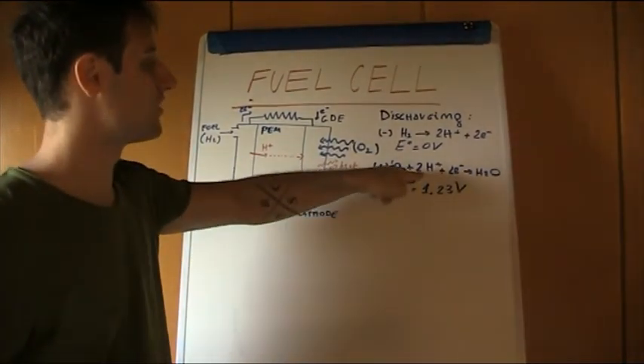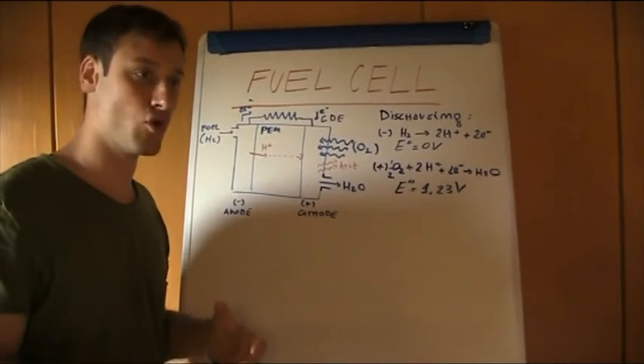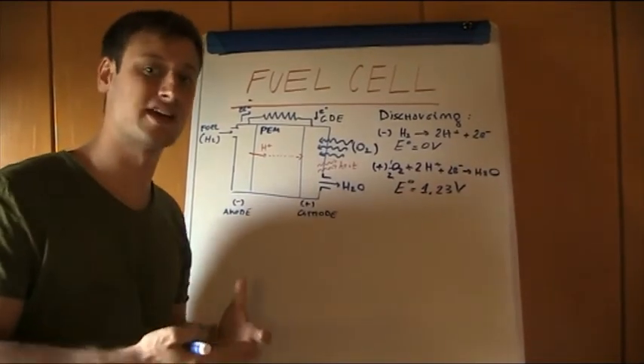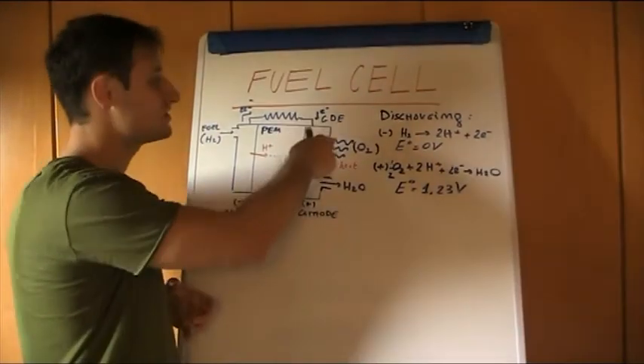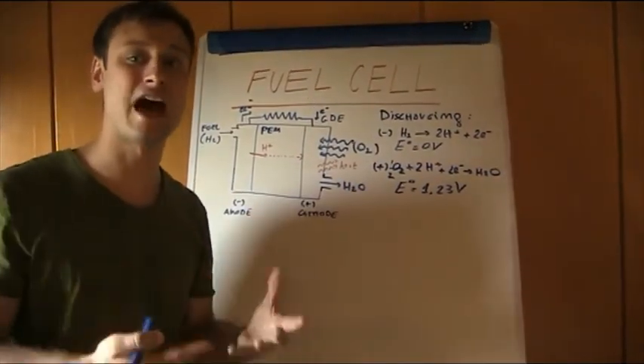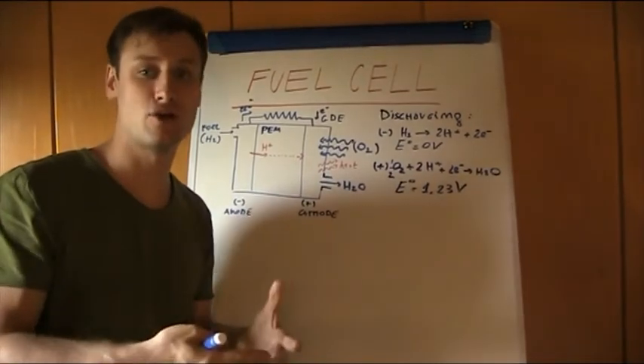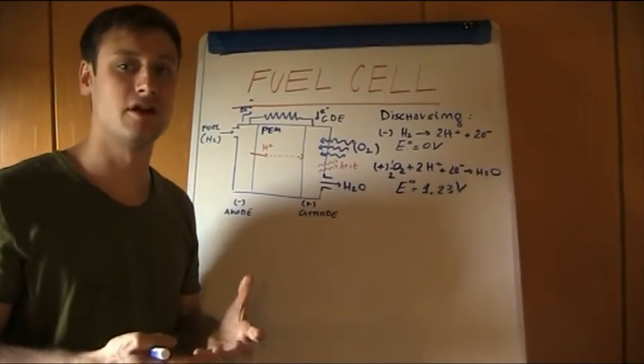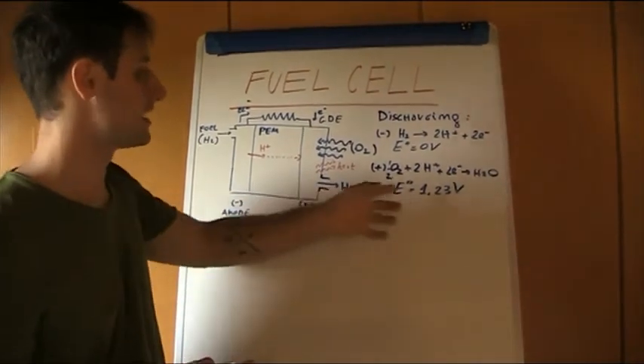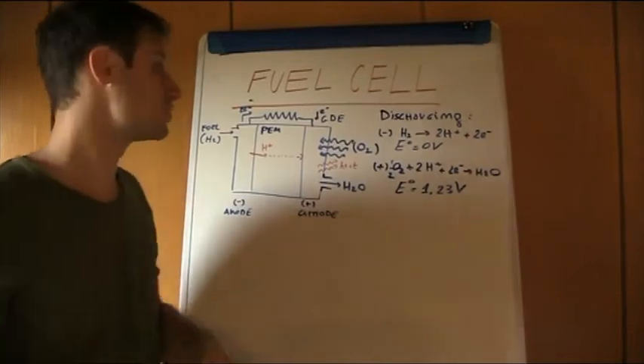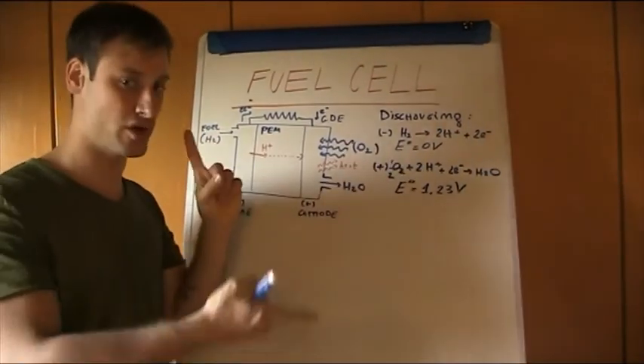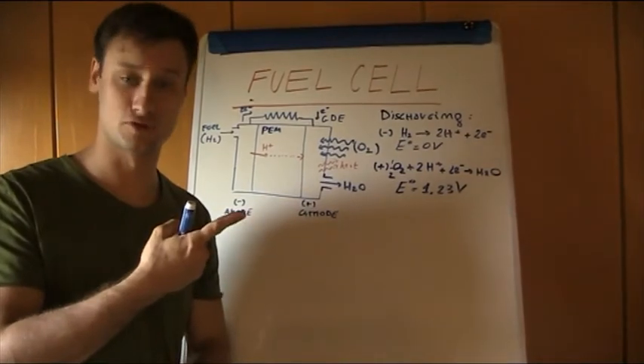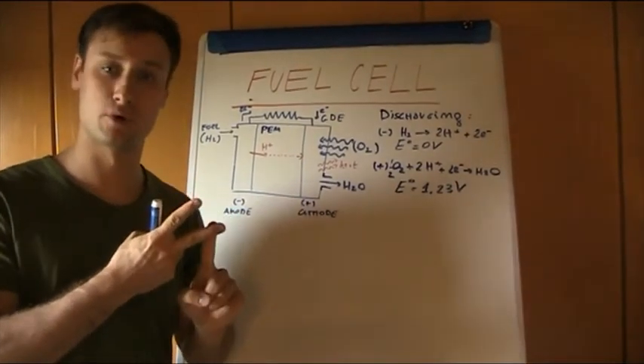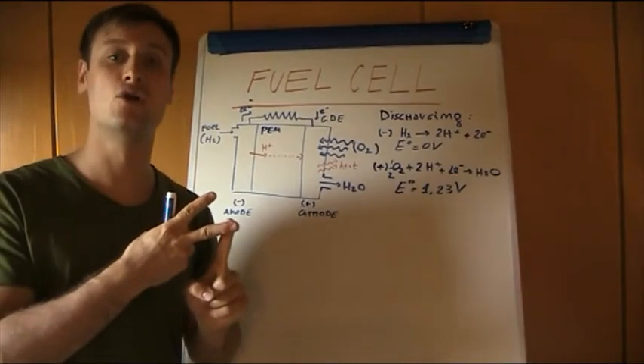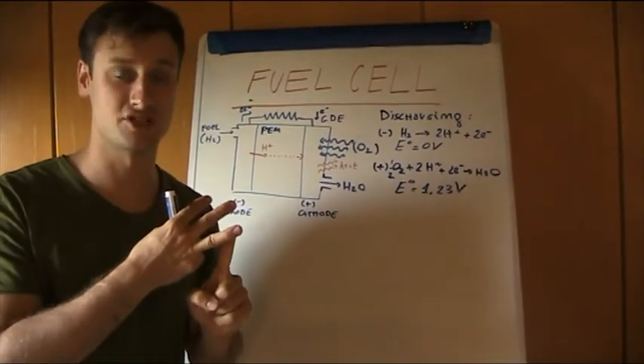And the passage of this H+ toward the catalyst can be ensured because even in the gas diffusion layer we can have a little amount of Nafion, a little amount of ionomer, this conductive polymer that allows us to convey this H+ toward the catalytic site in which the reactions occur. So we can say that the GDE in this case is composed of a gas diffusion layer made of carbon fiber. We have a microporous layer of carbon matter on which the catalyst, the platinum, is deposited.